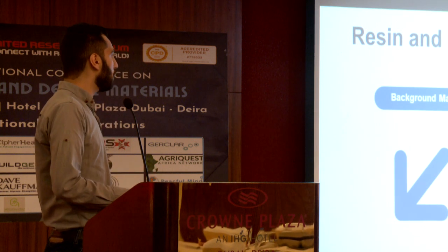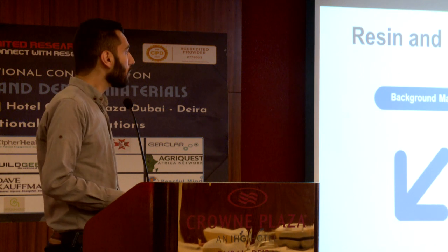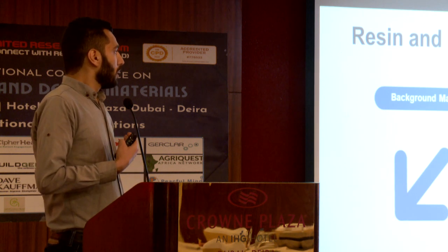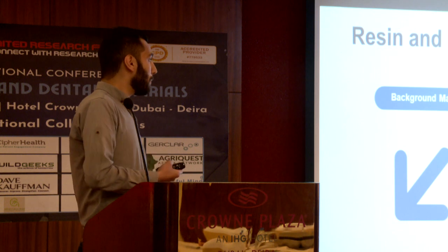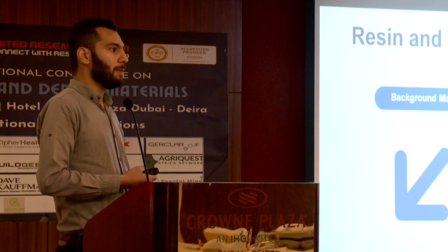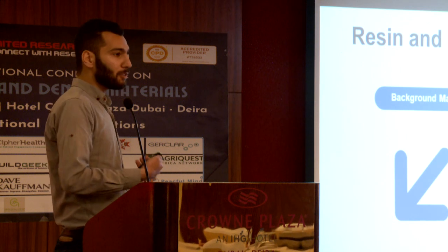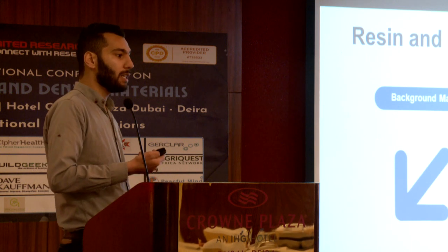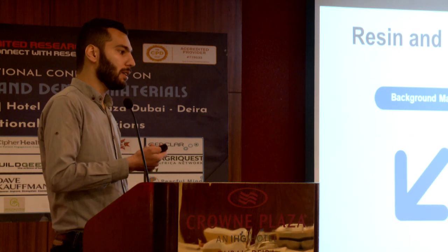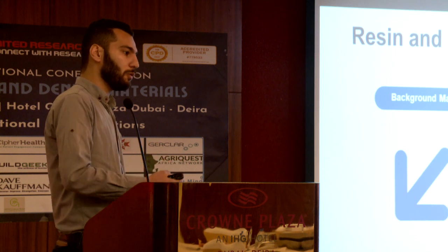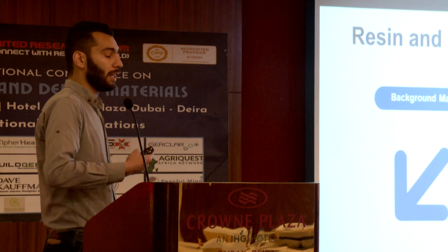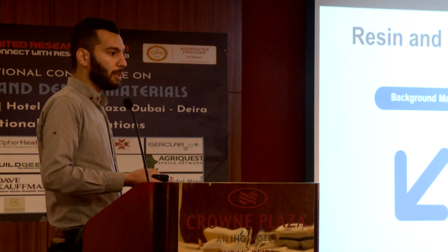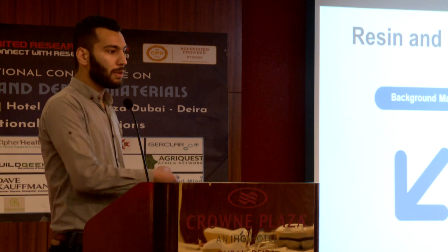So the best way to evaluate background masking is to evaluate shade change between the composite restoration resin and the abutment shade, which I control, like maybe A1, and the abutment I want, or the shade I want to mask. Like I'm evaluating if I'm able to mask shade A3. So I have to find the easy way and the better way. I have to find the shade change between a control shade like A1 or maybe bleach 4 and A3 shade.